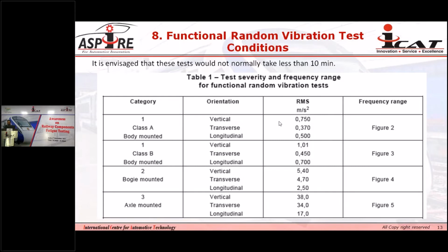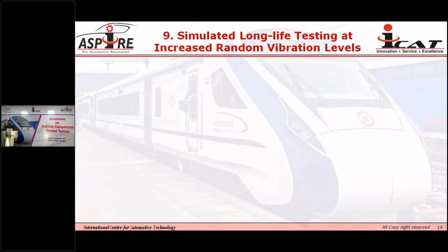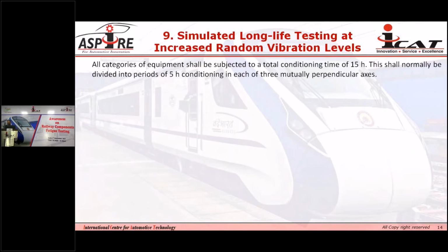During this testing, the equipment will be in the operating condition, meaning the functional test will be carried out during this testing. Now the next test is simulated long life testing at the increased random vibration level. The objective of this test, as we discussed, is to verify the mechanical integrity of the test component, and this is a total of 15 hours of testing, 5 hours along each direction: 5 hours along the vertical direction, 5 hours along the transverse direction, and 5 hours along the longitudinal direction.